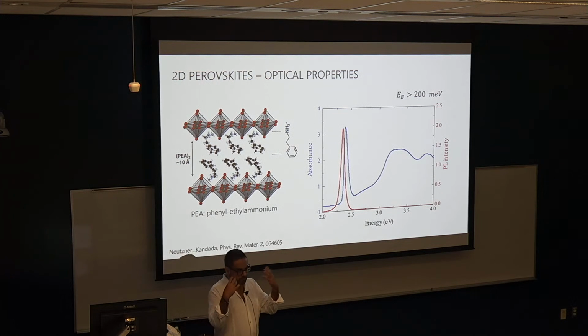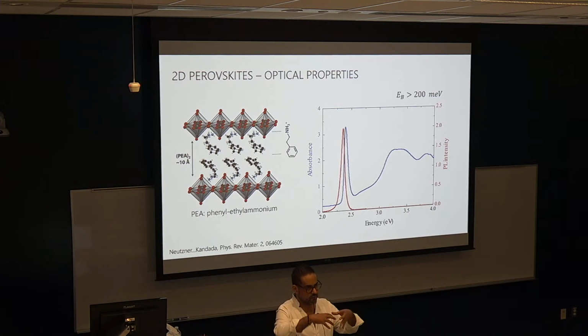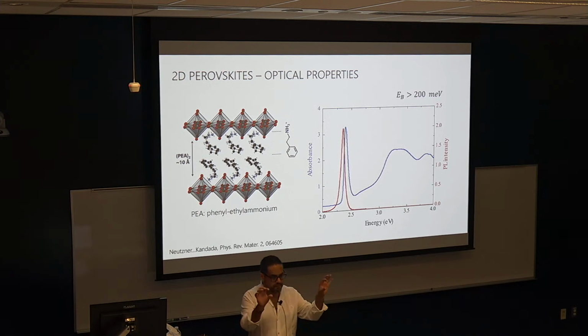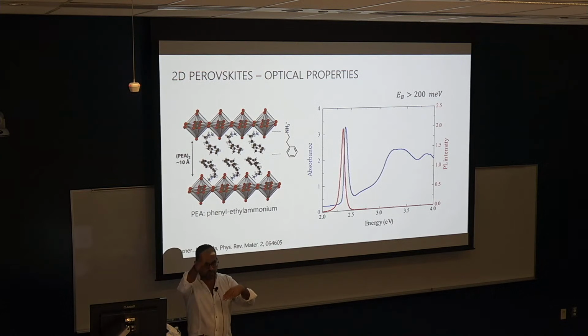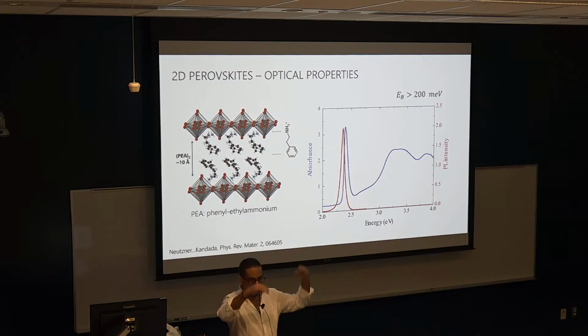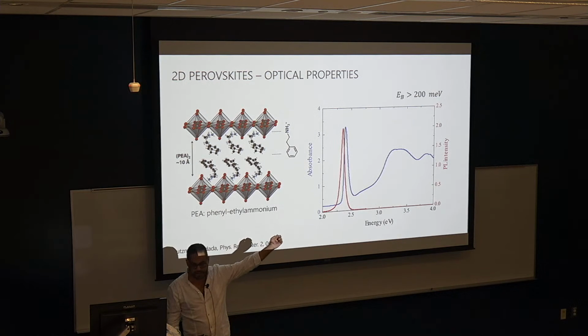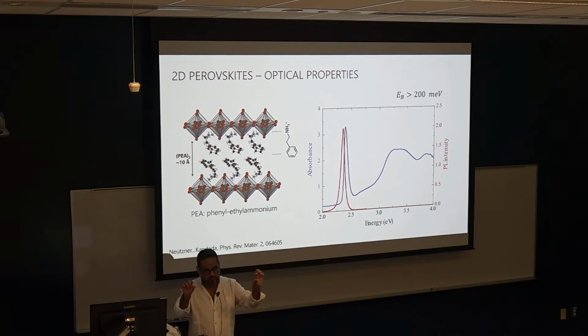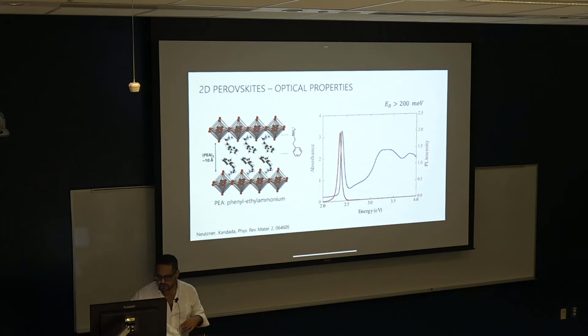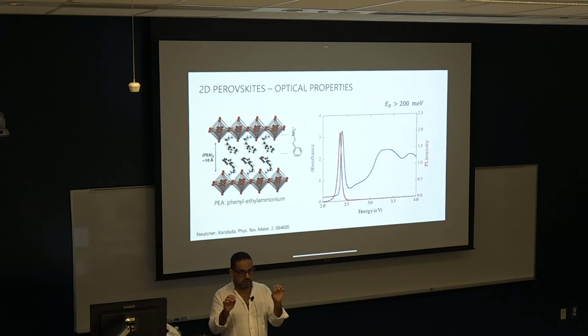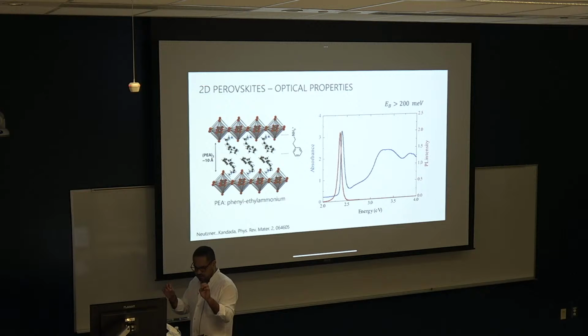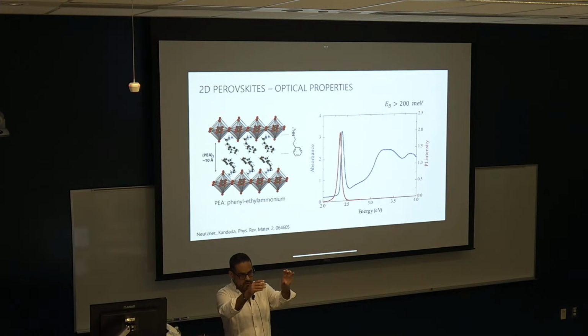layers. If you have a metal halide perovskite, a three-dimensional structure, and you just take one of these lattice planes, chop it up, separate it from the next lattice plane by these long cations, these long templating cations, you have a single layer of these corner-sharing octahedra, a single corner-sharing octahedra layer of these metal halide lattices, right? So you've got a single lead iodide layer, long cations, essentially vacuum, another layer, long cations.